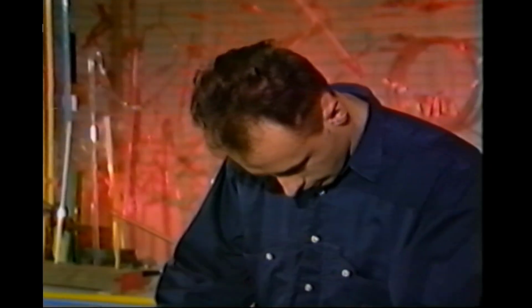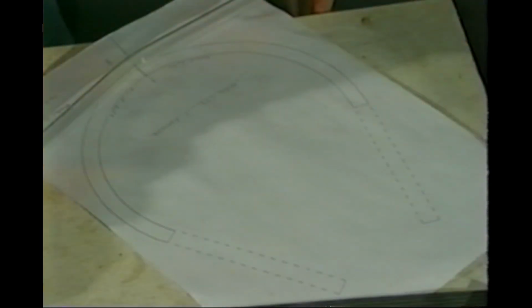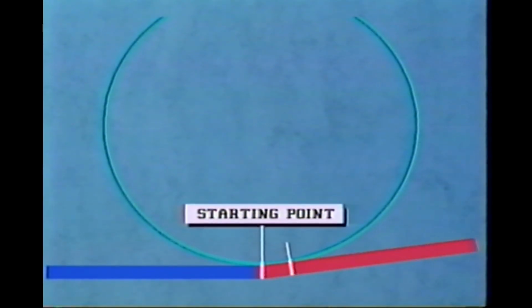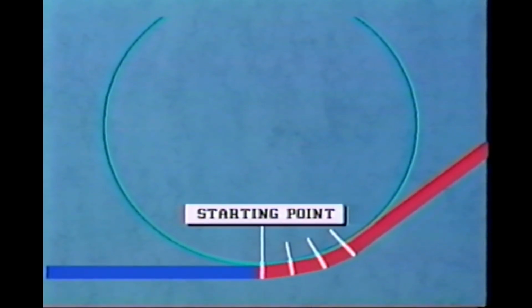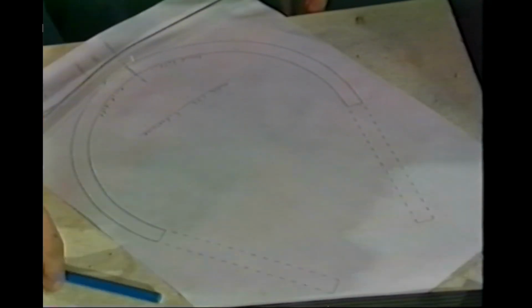Now, lay the tube over the drawing with the first mark on the center line, without making contact, and check the fit of the curve being produced against the curve of the letter C drawing. The bent area should follow exactly the inside line of the drawing, and the straight unbent length should leave the drawing at a tangent. The position of the next bend is now marked with the pencil at the point exactly where the inside edge of the tube departs from the inside line of the drawing.